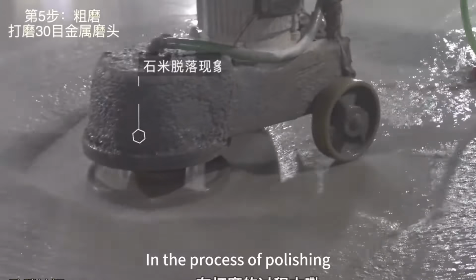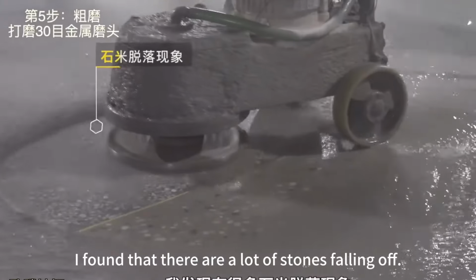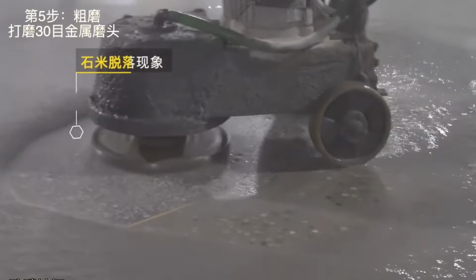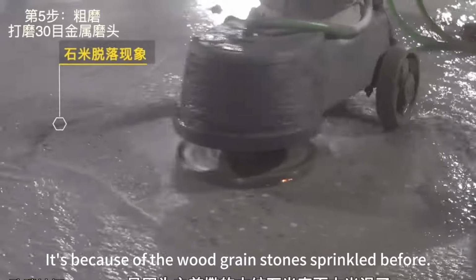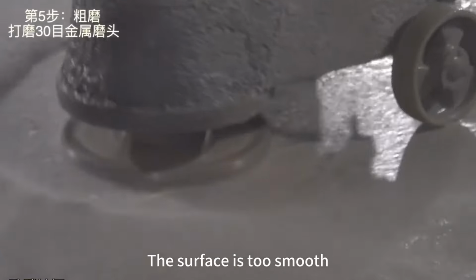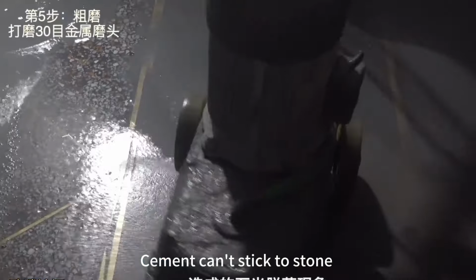In the process of polishing, I found that there are a lot of stones falling off. It's because of the wood grain stone sprinkled before. The surface is too smooth, so cement can't stick to the stone. This is the stone shedding phenomenon.